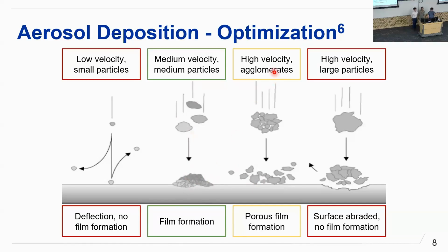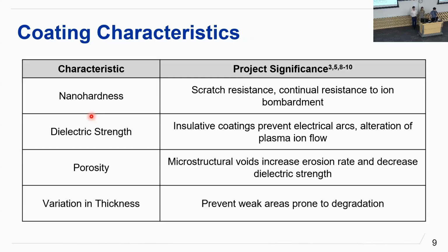Well, if we have too high velocity or agglomerates, as they hit, they'll spread out more and create a more porous structure, which is not desirable for a protective coating. As well, too high velocity or large particles will just start to sandblast or abrade the surface, and no film will be deposited. And on the other side, with too low velocity or too small particles, no film will actually be deposited onto the substrate.